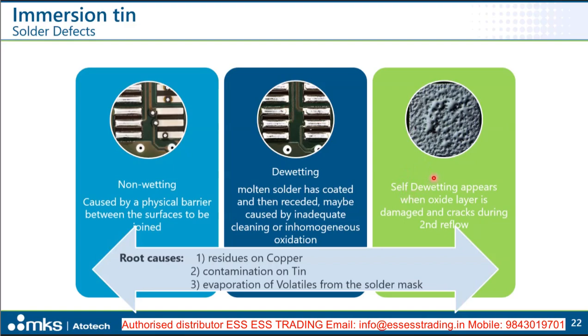And finally, the self-dewetting actually appears when the oxide layer is damaged, and during the assembly or during the reflow process, the liquid solder underneath, or the liquid tin underneath the oxide layer, cracks through the oxide layer, comes to the surface, and then hardens there, causing these kind of pearls on the surface. And actually, for all the three types of soldering defects, the root causes can be nailed down to being residues on copper and/or contaminations on the tin surface, or even volatiles from the solder mask evaporating in the reflow oven and then recondensing on the tin surface.